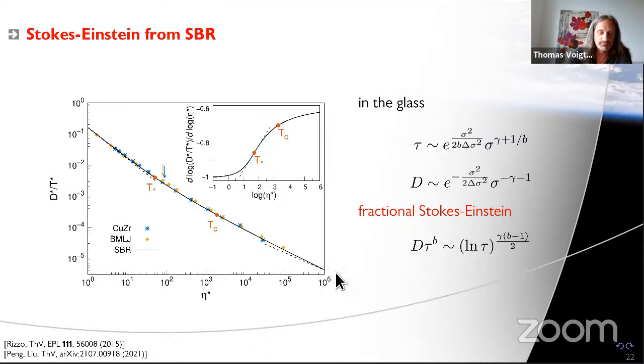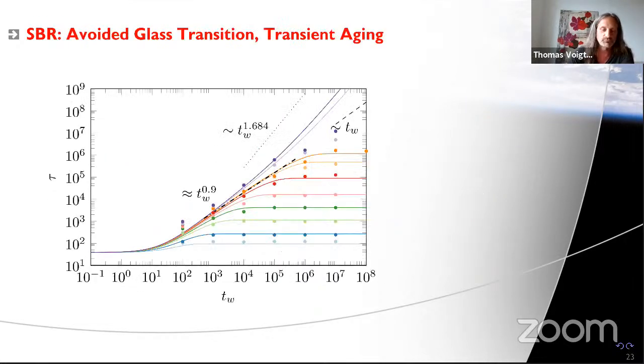And it is very well predicted by Tommaso's extension to mode coupling theory, the so-called stochastic beta relaxation theory, which is the solid line here. And so that, as an aside, I found motivating to investigate this theory further and to come back to our aging problem. So here's the plot again.